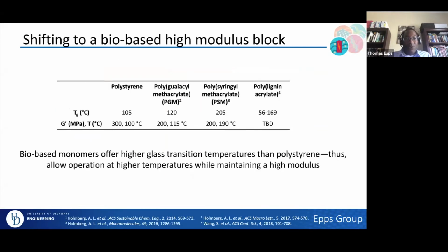So the other things that we can do that are quite nice is that, not only can we use these materials for things like adhesives, we can also use these bio-based materials, for example, as replacements or alternatives for polystyrene, where I want a material that is potentially just as cheap, but has a higher glass transition temperature. So you can imagine, again, now using, say, this guaiacyl methacrylate, we can go up to about 120 degrees Celsius, a syringyl methacrylate, Tgs above 200, or mixtures of other lignin methacrylates and acrylates that allow us to really tune in that range between, say, about 50 degrees and 170 degrees.